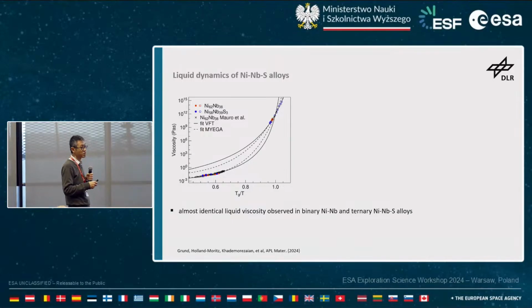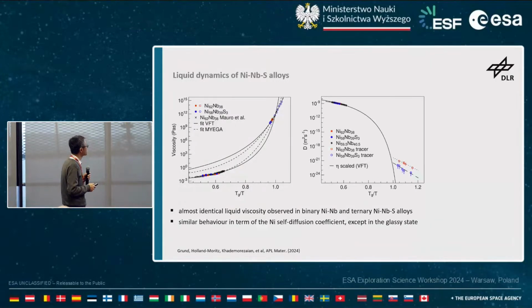And because it's a glass, if you're heating it from the glass transition, you can also study the viscosity at the low temperature. In both cases, what you can see here is that the viscosity is not changing much. This is the same if you look at the transport coefficient. Between the binary and sulfur-containing alloy, they have very similar transport coefficients, except that if one goes down to the glass, below the glass transition, then one sees some differences in the glassy state: the sulfur alloy seems to have slower dynamics.